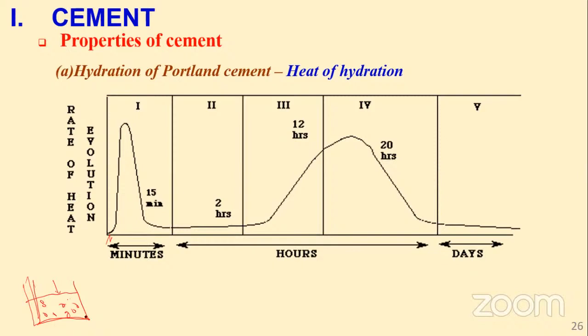So when you pour water inside here, you see, when the compound comes into contact with water, the tricalcium aluminate. So we are saying heat, as you can see, the rate of heat evolved is dependent on the time. So it's changing with time, as you can see from the curve. So the first stage we are saying is a hydrolysis of cement compound occurs rapidly. So the hydration occurs rapidly, temperature increases, the amount of heat, then it slows down.